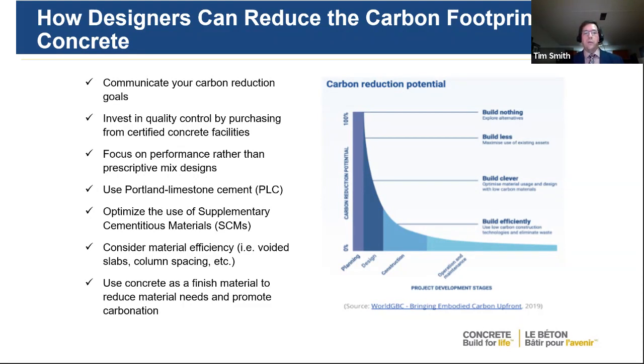They can give you the strength that you want and optimize your mix design. You tell them that you want a class C2 exposure, 32 MPa. They'll be able to provide you that with the right amount of supplementary cementitious materials in the mix to optimize the mix designs. And if you specify certain carbon reductions, they can work towards that goal as well. You want to have performance specifications rather than prescriptive, because if you allow the performance ones, it allows them better ability to optimize their mix designs.